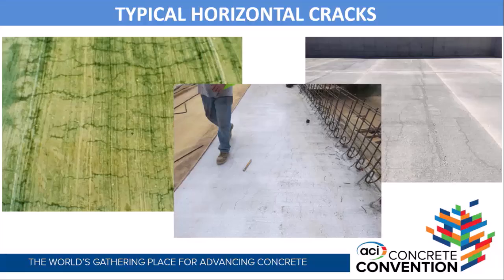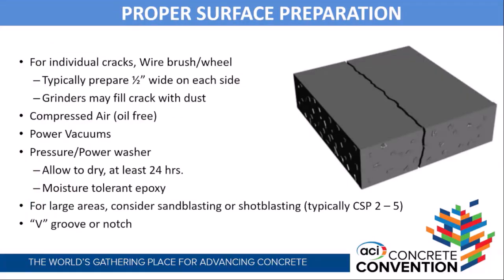You can see here in the photo on your right, that is a classic example of plastic drying shrinkage cracks, typically from wind, where you have a lot of wind coming over the surface. Now, normally those types of cracks are superficial. They stay right up at the surface, but they can propagate. They can get down to the reinforcing steel. And if you're allowing these contaminants to come in, water, chlorides, and carbon dioxide, you're going to get corrosion of your reinforcing steel. But sometimes you do get cracks that are individual. They're just linear. They're caused from restrained shrinkage, drying shrinkage, and you can treat those individually as well. So proper surface preparation.